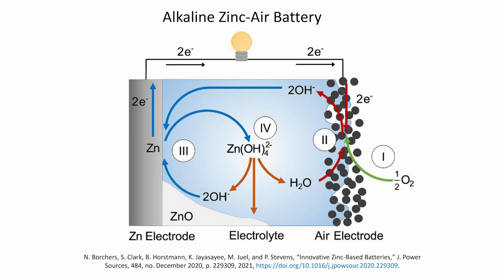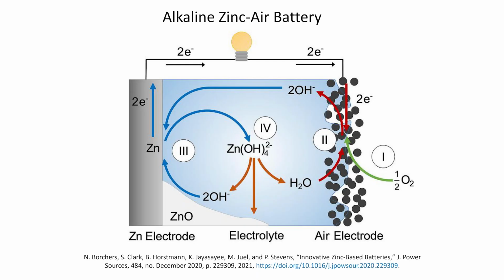And just for the record, what kind of materials are found in the electrolyte? As we mentioned, it's an aqueous electrolyte, which means that water is the solvent. And that's really nice from a safety and sustainability perspective. And into that, we dissolve usually potassium hydroxide in very concentrated solutions. And sometimes you'll also mix in some additives like zinc oxide to try to get it to where it's already saturated with zinc. You can add in some other additives like potassium fluoride or some carbonates to try to extend the lifetime. But fundamentally, water and potassium hydroxide.